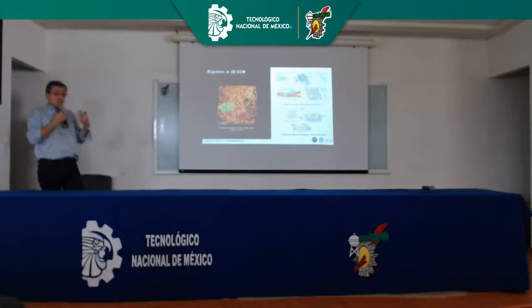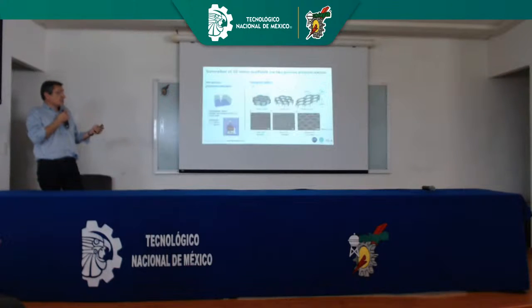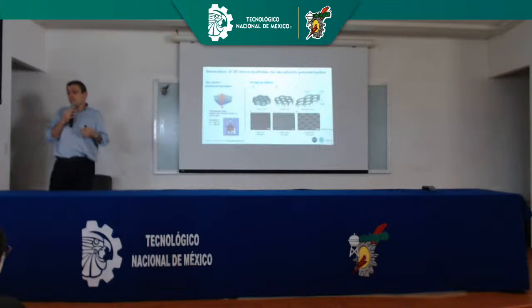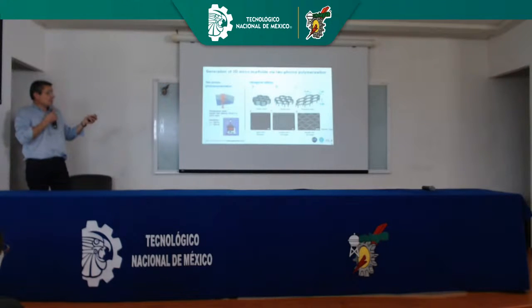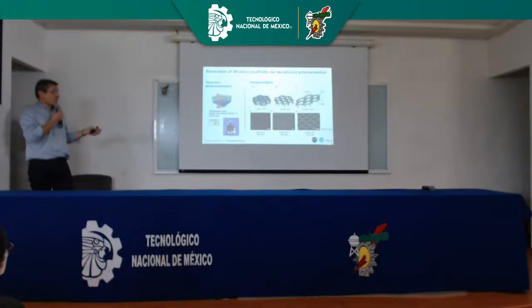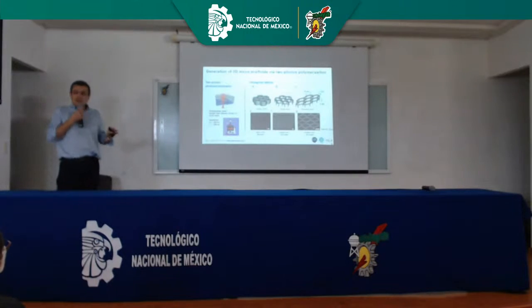So we started a project, and the idea was to create fibers using photopolymerization. And particularly, two-photon polymerization. We are using typically a pulse laser, and we are able to polymerize at the focal point, and by moving the stage containing the monomer, so this gray part is a liquid monomer, you can polymerize any kind of structure. So typically here are some examples of the first structures that we have designed. It's not ambitious in terms of fibers, but it was a start.